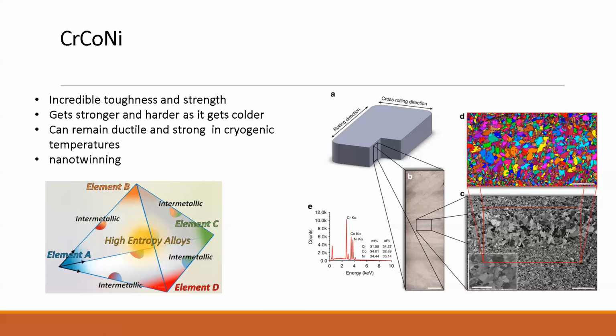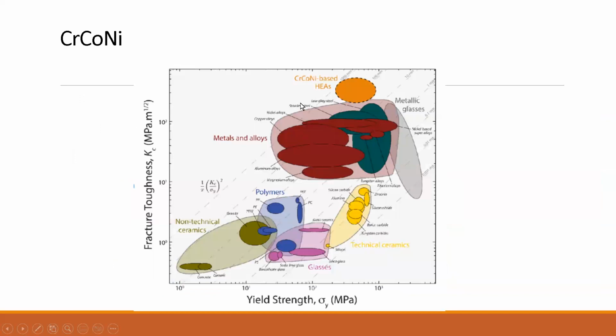And it owes this increasing strength to a mechanism called nanotwinning, which is about the orientation of these lattices. They behave like a barrier for dislocation motion, and it gives them more strength by doing so. So as we can see, we can compare these chromium cobalt nickel based high entropy alloys with other materials. As you can see, it has a higher fracture toughness, and it also has higher yield strength. So this ratio is really good with chromium cobalt nickel alloys.